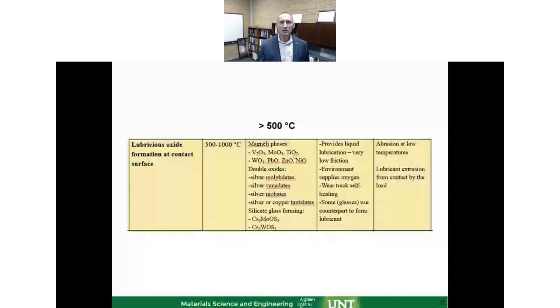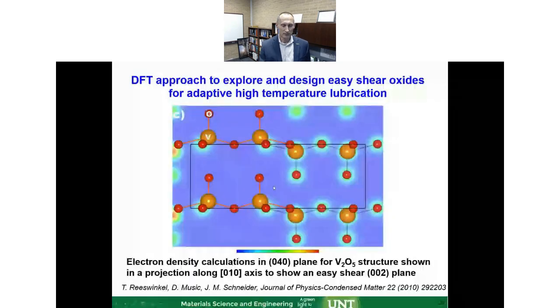Okay, which ones do we need? Well, we want ones which are stable at this temperature and have low friction, meaning low shear, or low shear modulus oxides. Magnéli phases or defective oxides like tungsten trioxide and molybdenum trioxide, some of those listed here, are of course among the choices. And people working in the tool industry well know the benefit of the addition of vanadium to the hard coatings from that perspective. Then you can look at double oxides, which can help to reduce the temperature at which the mechanisms get triggered. And here we can also rely on a modeling tool to help us, because that material domain space becomes very large very quickly, with the multiple transition metals and oxide structures available. And now you're adding double oxides, which extends it even further.